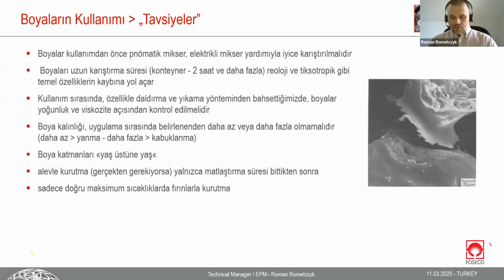Another one, if it's needed, don't rush, don't be in a hurry with it. Wait some minutes to give a chance to finish some kind of matting time, so the mold or core stops being shiny. It means that the alcohol disappeared inside. The core or mold sucked it in and some evaporated, and after that we can burn it out, put it on fire. Why? Because if the coating disappears inside and outside, and evaporates a bit, the energy created during the flaming will be less.